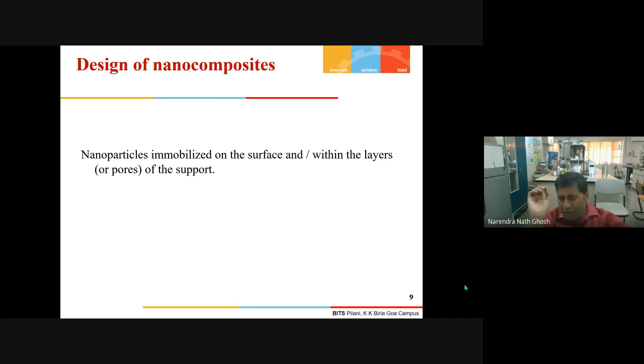Therefore, we have dispersed or anchored these nanoparticles on the surface of some support. So what will happen? The size of the catalyst has increased, but these supports play a dual role. One, due to the high surface area, the reactant molecules first adsorb on the surface, so the reaction efficiency increases, because that gives more chance to the reactant molecules to come in contact with the catalytically active sites. As the active sites are anchored on the surface of the support, that reduces the chance of agglomeration. Another thing is that we have anchored the nanoparticles on the support in such a way that their chances of leaching out are also prevented.